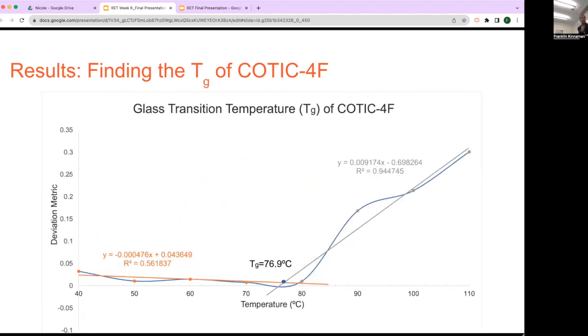So when I did calculate the Tg, I was able to find my best fit lines where they crossed over. That came at about 76.9 degrees Celsius. And as you can see on the x-axis, I had to exclude everything above 120 degrees. But this is the result of about 7 or 8 data points total, I think. And when I started out this process, I used far less data points than that. So the more data points you have in a graph like this, the more accurate your temperature will be.